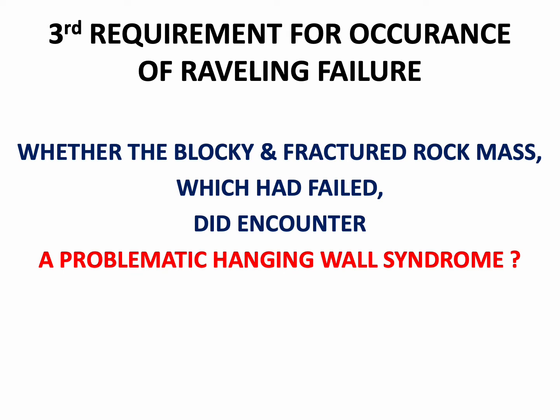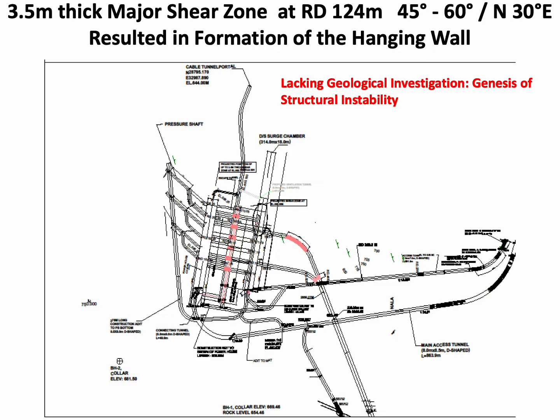The third requirement for occurrence of raveling failure was whether the blocky and fractured rock mass which had failed did encounter a problematic hanging wall syndrome. Let us find out. There was a 3.5 meter thick major shear zone at RD 124 meter with an inclination of 45 to 60 degree with an orientation of N 30 degree east, which resulted in formation of the hanging wall.